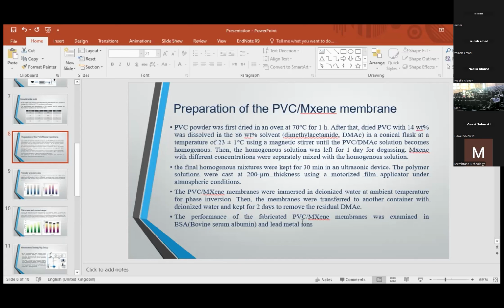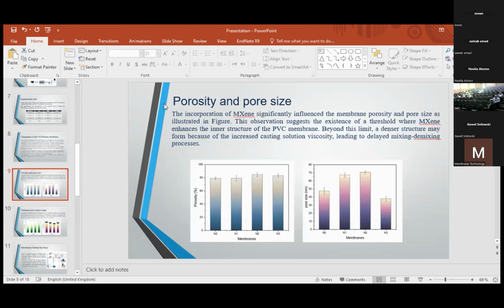The performance of the fabricated PVC MXene membrane was examined in BSA, bovine serum albumin, and lead metal ions. The porosity and pore size: the observations suggest the incorporation of MXene significantly influenced the membrane porosity and pore size as illustrated in this figure. This observation suggests the existence of a threshold where MXene enhances the inner structure of the PVC membrane.